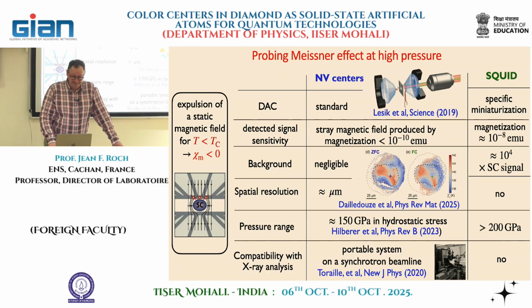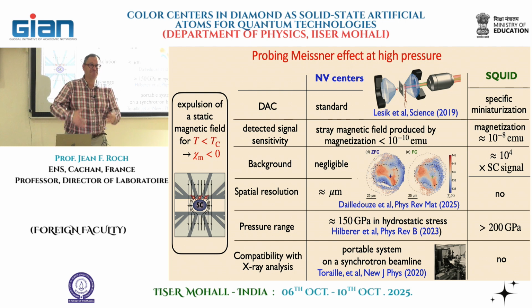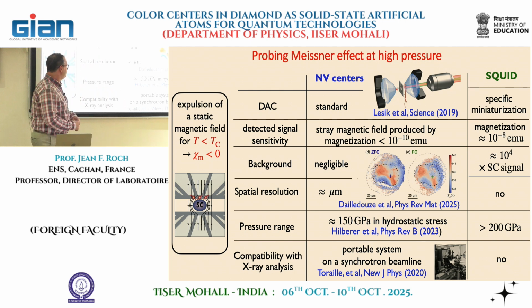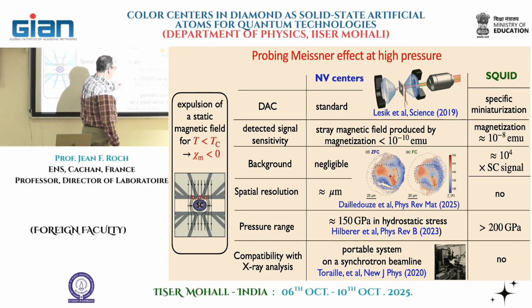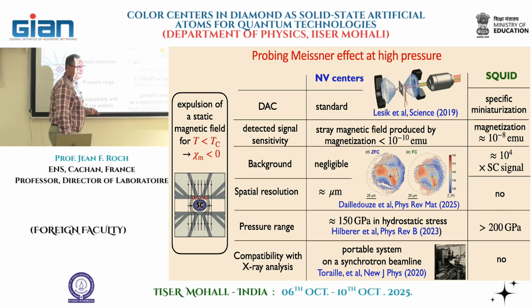Okay, so we can compare, for instance, benchmark our technique to SQUID. And of course, it's rather difficult to always say I'm better than another technique. But I would like to highlight two main differences. The first one is we're able to work in the same range, and we do not need a specific cell. We have a sensitivity that we believe is higher. We have no background. This is an important advantage.